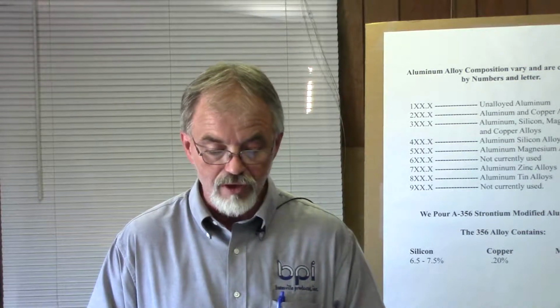There are two main modifiers, sodium and strontium. We use strontium because it works better in a permanent mold application. Running the melt temperature high or letting the melt stand for a long time allows the strontium to burn out. We make additions to have active strontium in the melt.